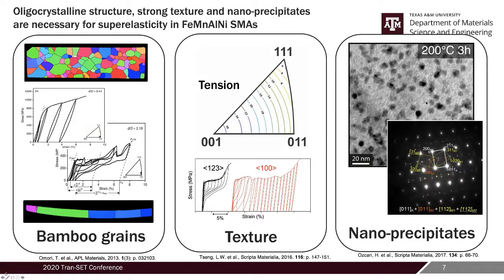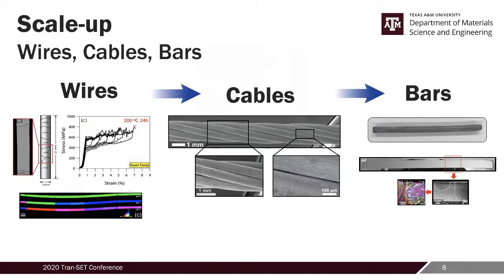And the last one is, after you grow your grains, you want to strengthen your material, and you achieve this by inducing nano-precipitates in the material by low temperature aging. So in my talk, I'm going to talk about how we can develop iron-based SMA wires and then switch to cables and bars.